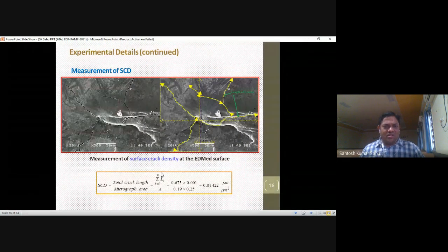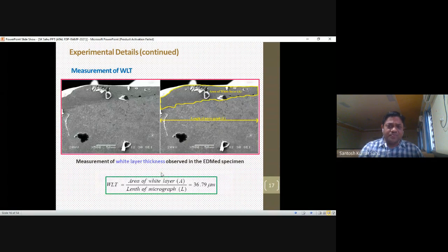Again, we have to see the surface crack density. It is a very important thing. The surface crack density is the total crack length divided by the micrograph area. We have to get it from your SEM diagram, using an image analysis tool, and from that we can measure the crack density. Why do you have to measure the crack? Because if you do not minimize the surface crack, it is again one of the limitations of that machining, because a crack is the initiation of any failure of your metal. So it should be minimized. You have to take care of the surface crack density during machining.